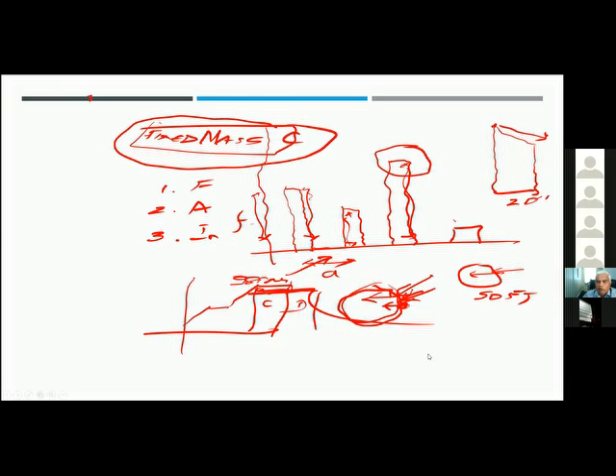No, the low pressure that I am talking of is, for example, let me try to draw another graph. This is 1000 millibar. The horizontal line is 1000 millibar. This is the atmosphere. Now we come to 10 minus 2 millibar, which is 0.01 millibar. This typically represents about 2 ppm of oxygen. So what we do in the system is we first pump it down from atmosphere to some 10 minus 2 millibar. So we are somewhere in this level.